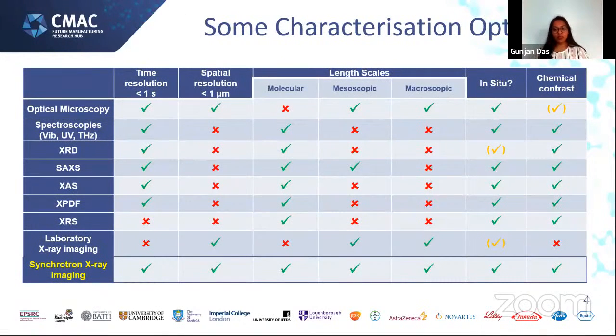Many techniques have been applied, but not all of them have been able to provide the required information, and there have also been limitations with experimental setup. The ideal technique should provide structural information and also imaging insight, provide information at a molecular level, and have some spatial and time resolution. As we can see, not all the techniques shown on the table tick all the boxes. However, synchrotron-based X-ray imaging ticks all the boxes, making it an ideal technique, especially considering nucleation is a multiscale process, and it's a rare stochastic process, so this would be a very suitable technique.